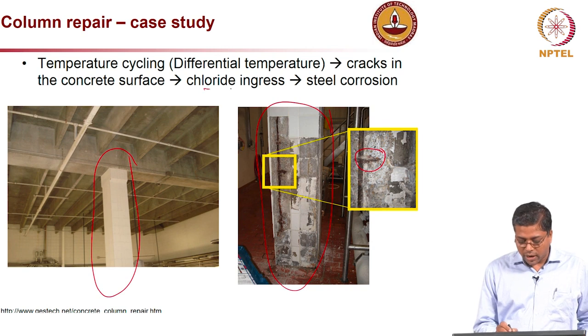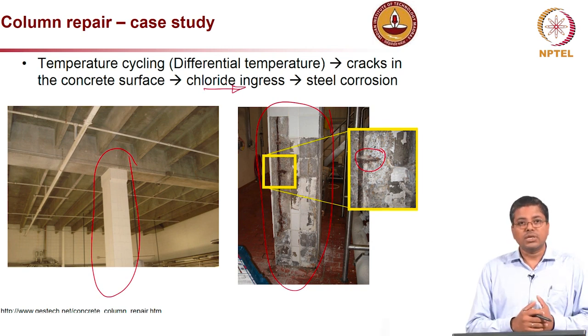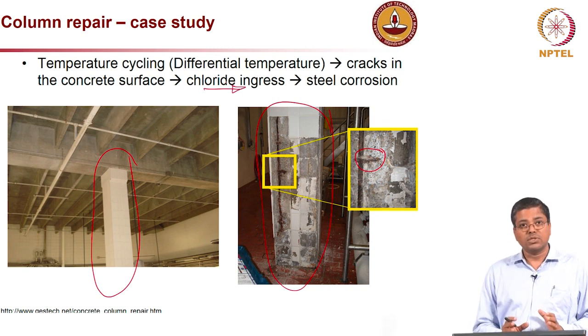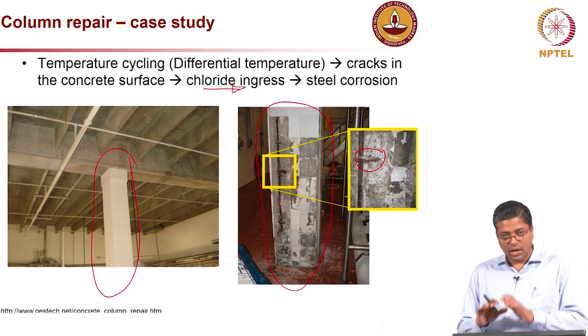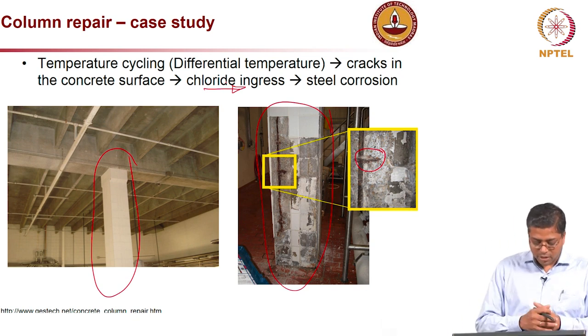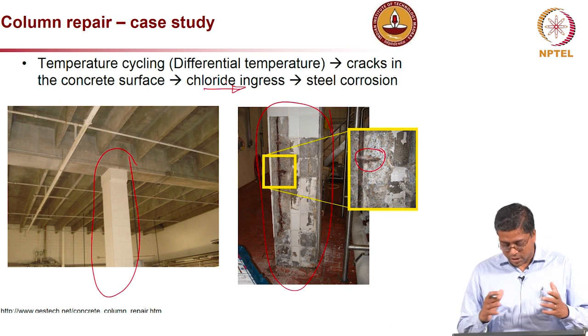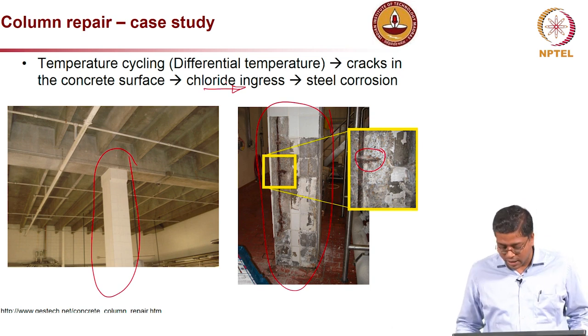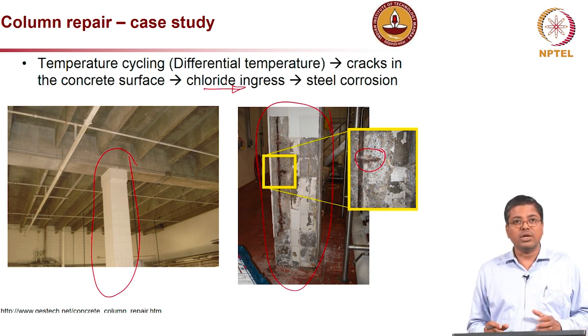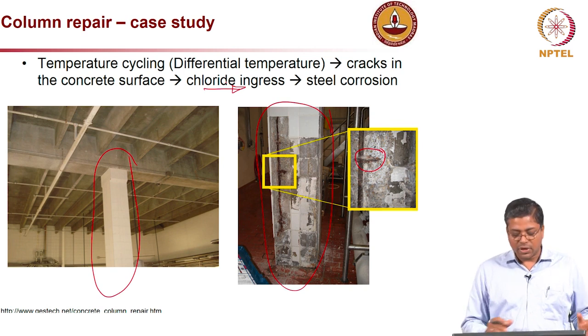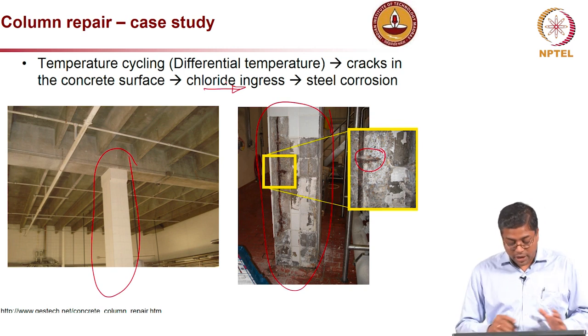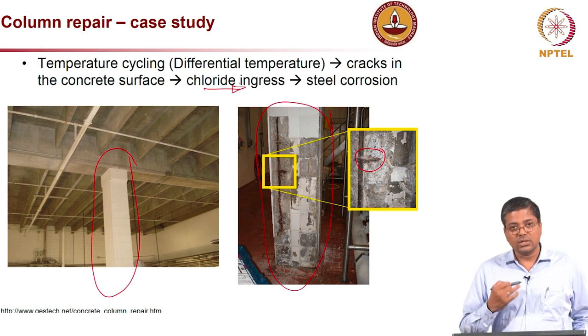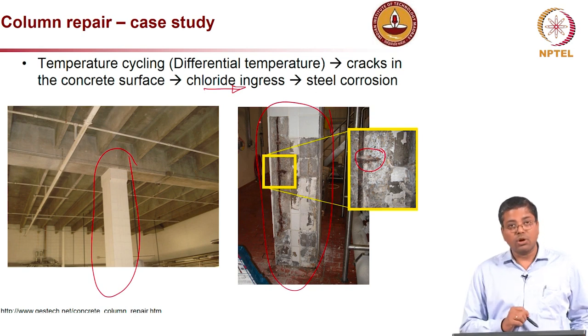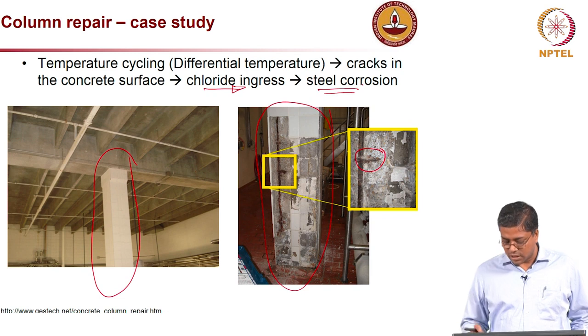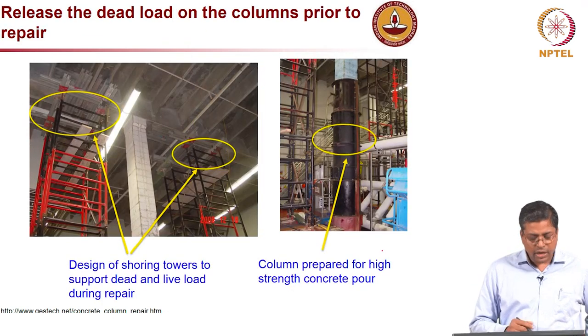So, chloride ingress was high, especially where the temperature was more, at the bottom, where there was some chemical equipment pumping high heat. So, you had high temperature and at the same time a chloride environment, which led to ingress of chlorides especially at the bottom of the column and then eventually steel corrosion. And then how do we repair?